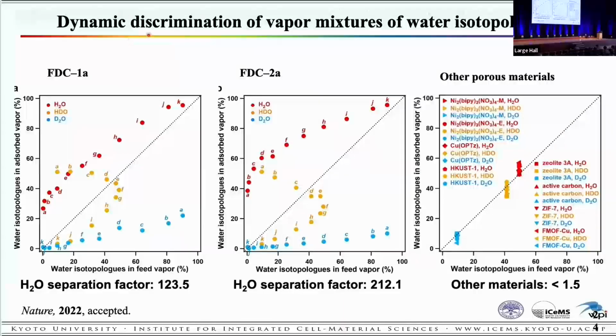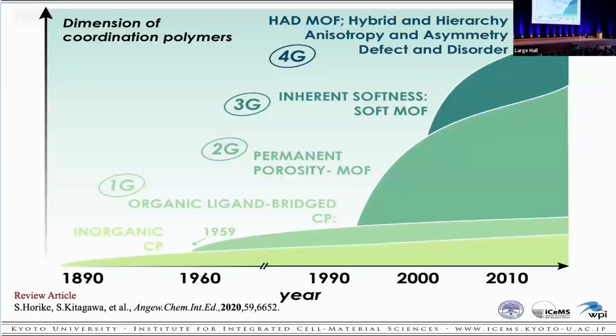So this is the dynamic description of a mixture of water isotopologues using mixed vapors. For instance, this is water isotopologues in the feed vapor, and this is water isotopologues in the adsorbed vapor. If the points are located on this 45-degree gradient line, no selectivity is obtained. But in our system, for instance, at very low concentration of water here, after the separation the content increases from the very small one to the large one. The other compound showed like this. So this is very useful, using this kind of local dynamics for the separation and controlling the gas molecule kinetics.